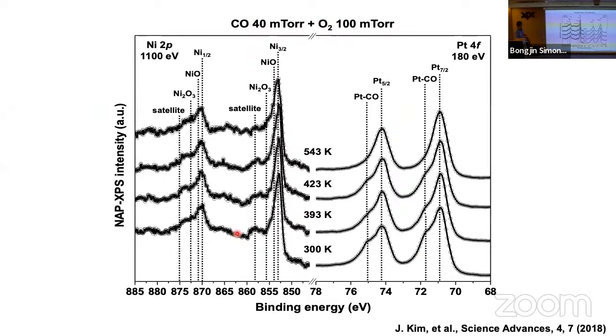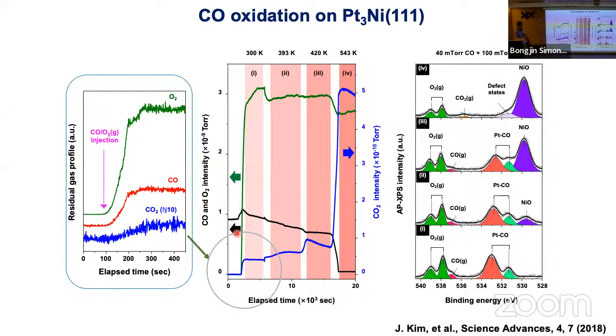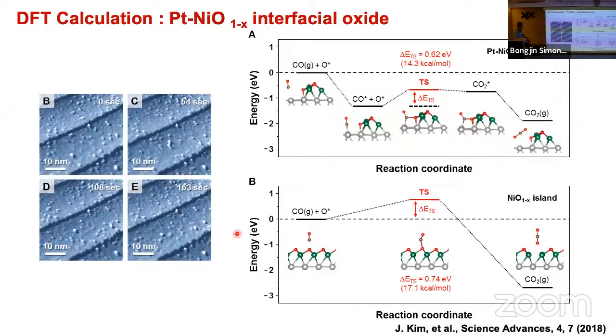And then this is another, similar experiment, but basically we were able to correlate the idea of the metal oxide that forms on top of the nickel to reactivity and CO oxidation, how that occurs. And what we realized was that the very surface of all this small clustering is actually very reactive. Well, that's what we found experimentally. And so we went to the theorists to explain this. And the DFT people suggested, okay, we have to try many models, but we sat down and thought about it. And then what we realized was that the oxygen forming in here should interact with both platinum and nickel. In other words, a platinum nickel interfacial oxide is probably the origin of this small clustering.